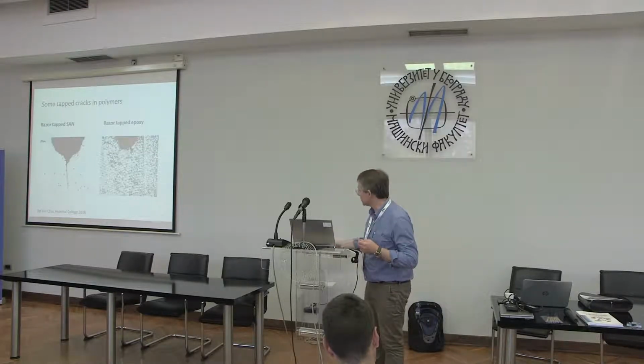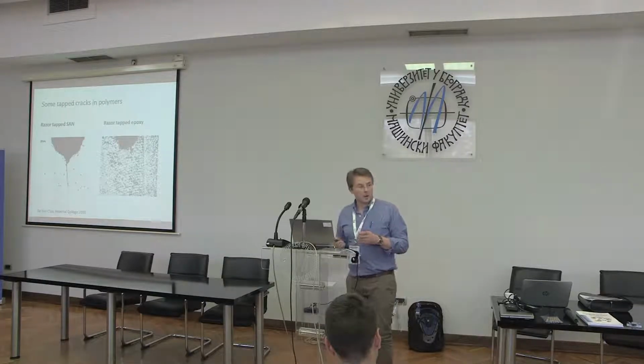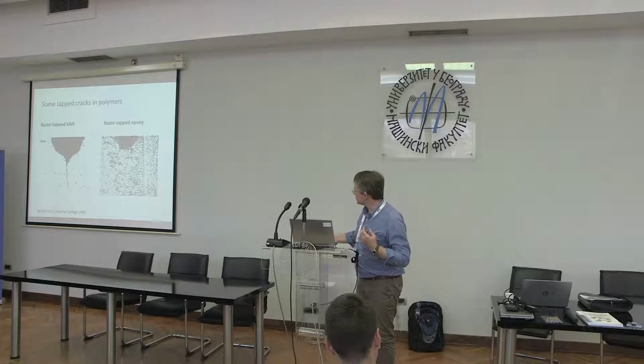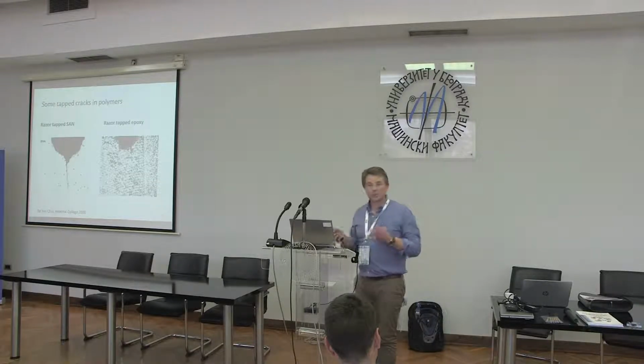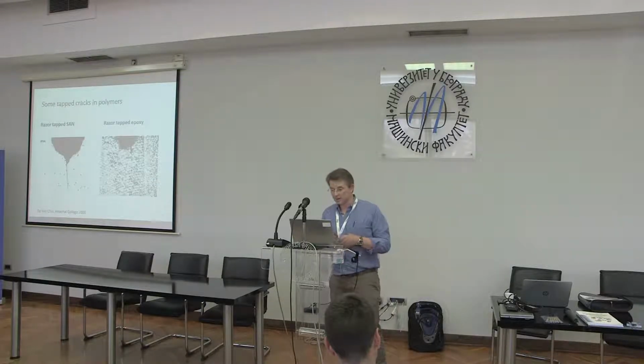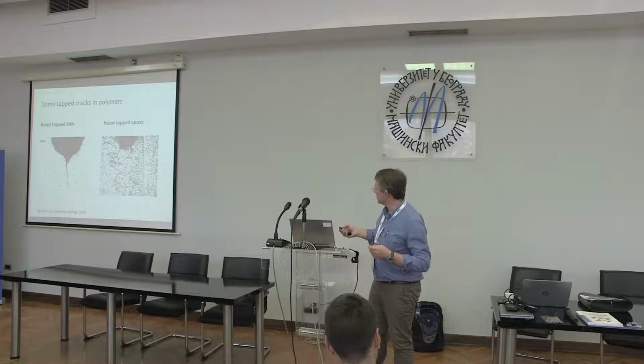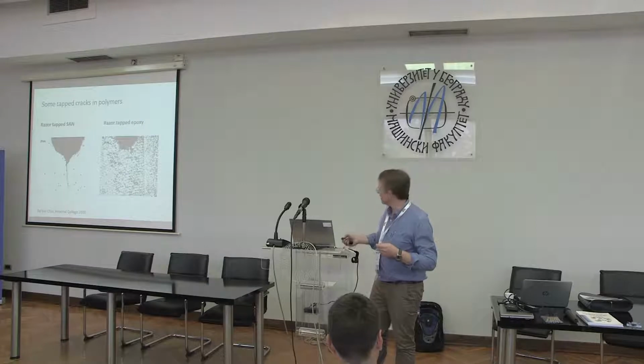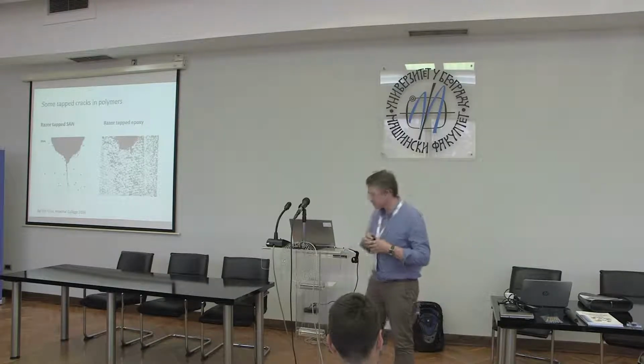We think about the notch tip radius down there, it's going to be very sharp, so very sharp crack, but the problem is that we haven't been able to control necessarily the length of it, we haven't been able to control the direction of it. And that's also been the case with the epoxy specimen here. There you can see our initial milled crack, and then there's our razor tapped crack.